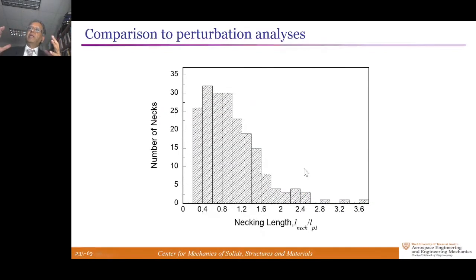There are attempts to do linear stability analyses where you take the uniform expansion and perturb it with a sinusoidal perturbation over the entire specimen, watch for the fastest growing modes and say those are the ones that will dictate the spacing. If you compare with such analyses, so this is the neck spacing observed divided by the neck spacing predicted by a linear stability analysis, you should see a peak at 1, but more importantly, you shouldn't see large amounts of unnecked regions, which is what we observed in the experiments. So we've actually questioned the suitability of the linear stability analysis to be predictive with respect to neck spacing.